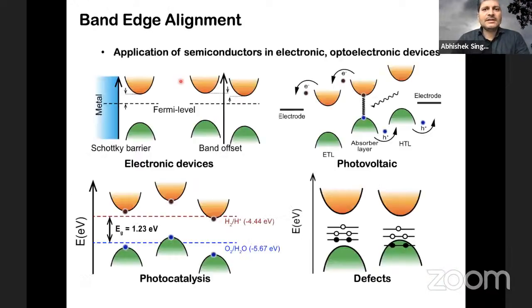Okay, so after that, the next application we looked at is the band positions, which are also unfortunately not predicted accurately in DFT. And once again, we use GW to get the accurate positions of the bands. And so these are the various applications of these band positions in electronic devices, whether it's an ohmic contact versus Schottky contact, band offsets, whether you find type 1 or type 2 interfaces, which has its own advantages for optoelectronic devices.